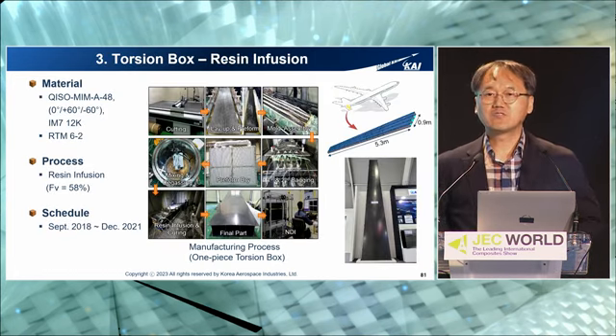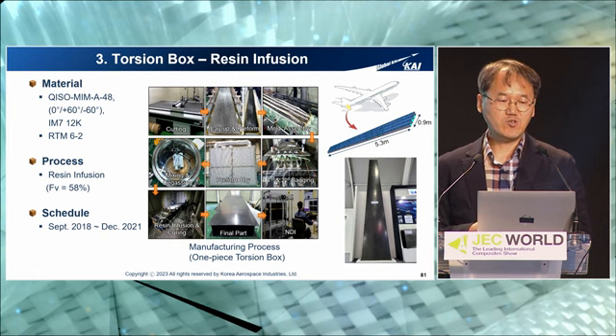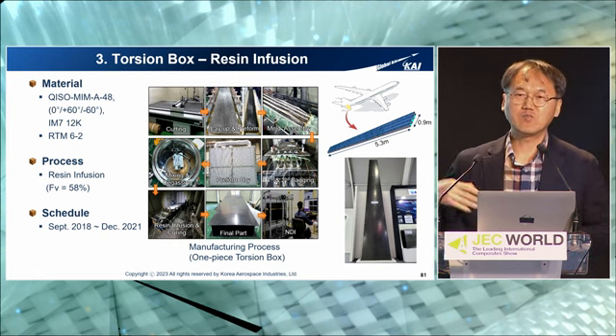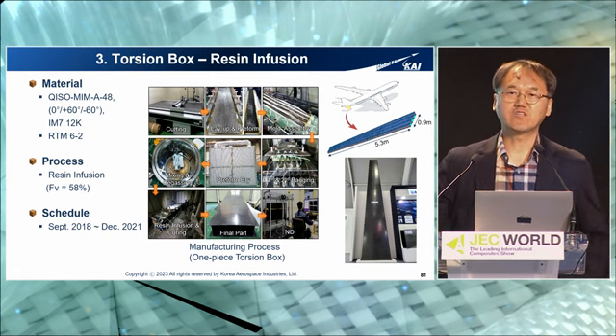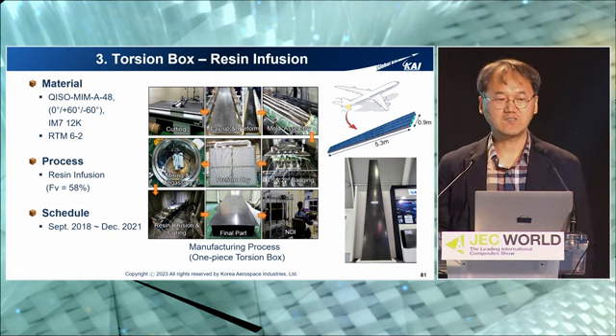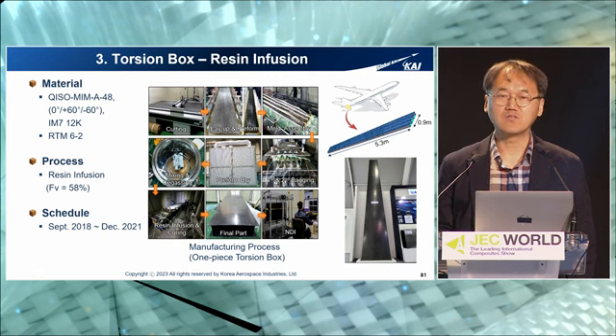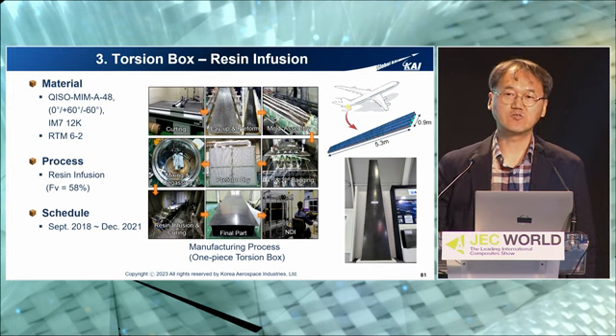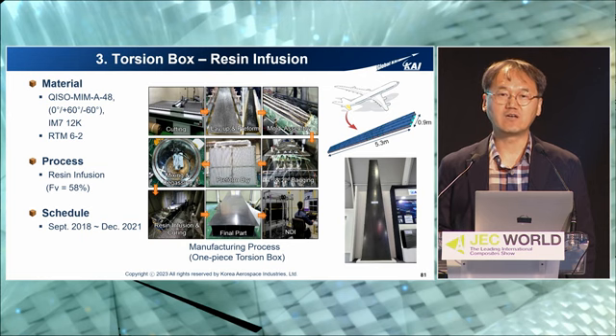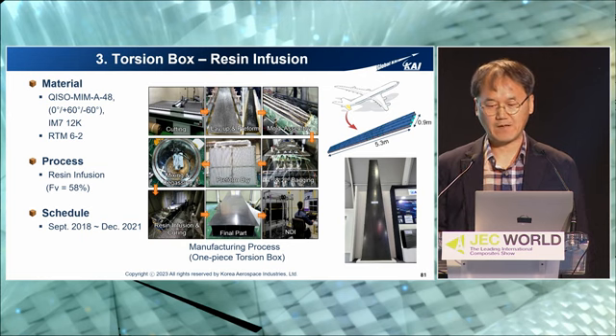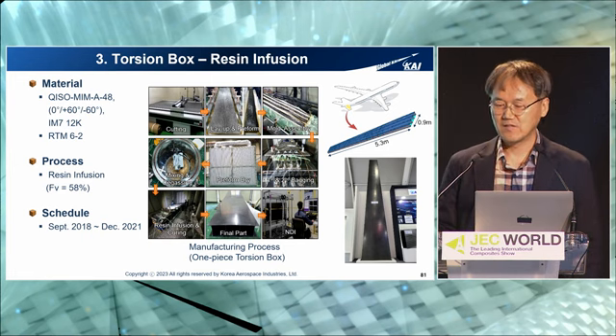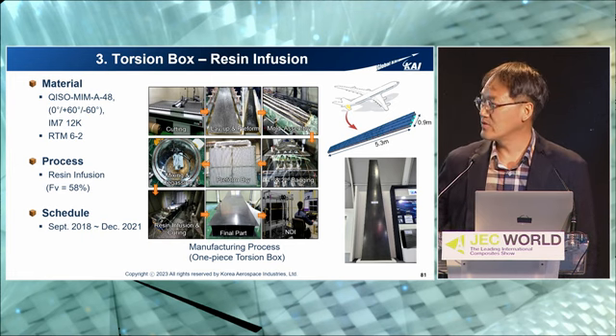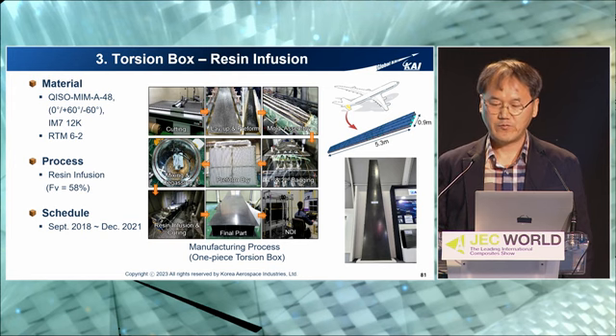The third topic is the torsion box made with the resin infusion system. The main difference from the previous large wing skin stringer module process is that we selected a QISO material system, which means 3 different layers woven as one layer. It means 0 degree, 60 degree, and -60 degrees layup as one ply. You can see the part size on the right-hand side of the picture: 5.3 meter by 0.9 meter.